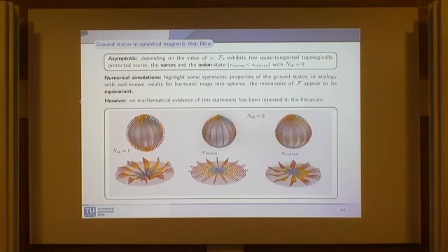I could ask you a more technical question. Can one include a DMI term on a curved surface? Is there a standard way to write that? Yes, there is the possibility to write the DMI term also for the surface. Some part of the contribution of this DMI term will go into the anisotropy energy, and some part of this will give you a tangential curl.